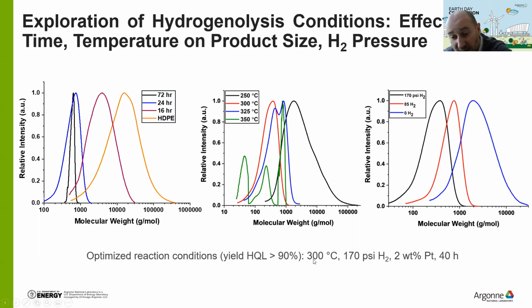And we found out that the best condition, in a batch system, is 300 degrees, under 170 psi of hydrogen, at 2% weight loading of platinum. As I mentioned before, this can be recycled infinite time, and 40 hours in a batch system. What we are looking at right now is moving from a batch system to a flow system, and I hope in the next few months to report some interesting results on the flow system, because this is going to be another real breakthrough, particularly for the engineering side.